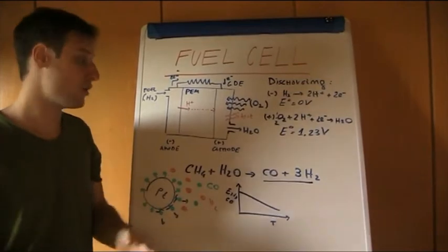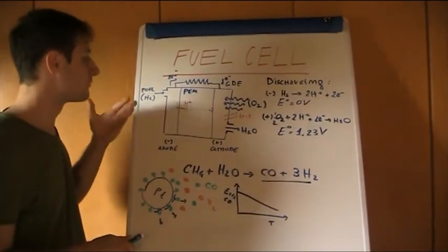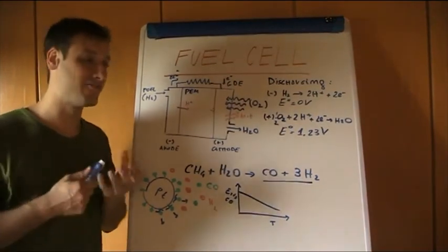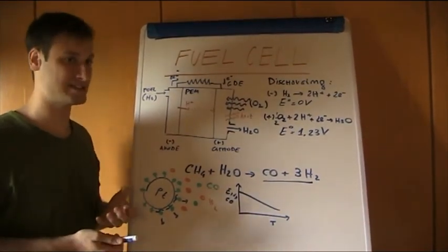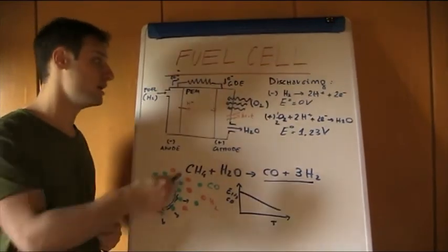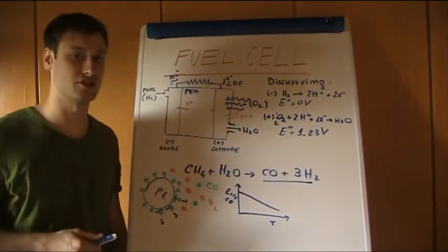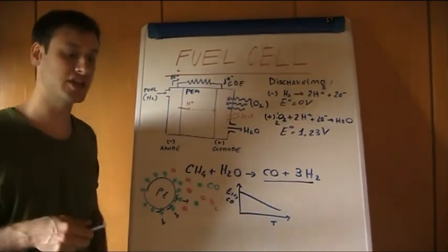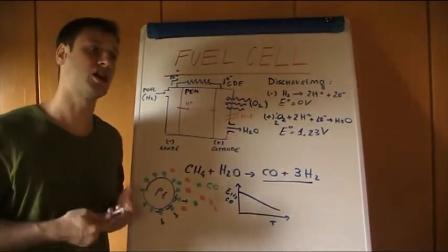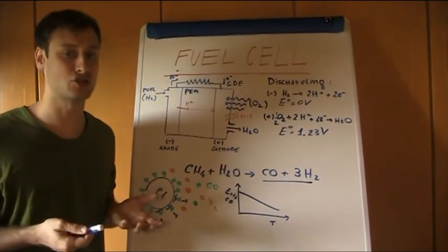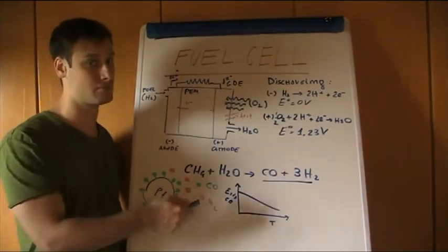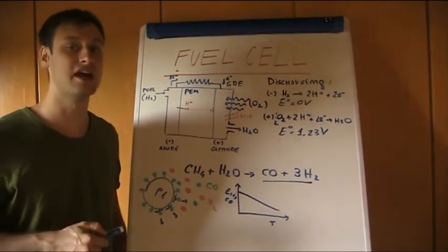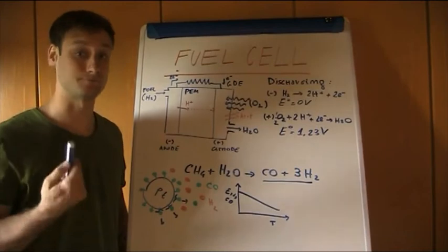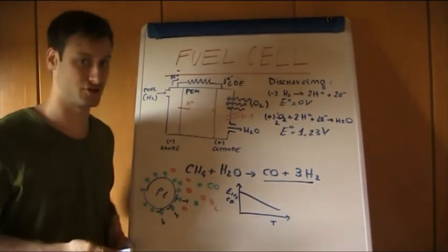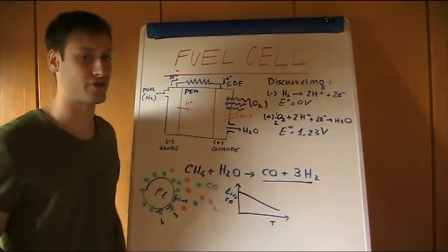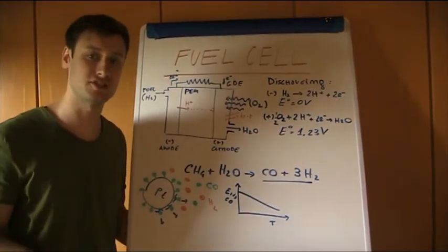They should be pure. Obviously, we can even use some traces of ruthenium in order to avoid this effect, but ruthenium is quite expensive. It is often used also in the gas diffusion electrode, ruthenium together with platinum, especially in all those types of fuel cell in which carbon dioxide is a product of the reaction. Why? Because even if not as strongly as carbon monoxide, carbon dioxide can also cause the poisoning of the electrode.